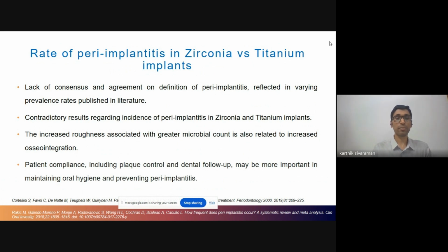The other aspect is for increasing the bone implant contact and increasing the osseointegration, we have increased the roughness of the implants. However, when there is gingival recession of the tissues around the implant and exposure of such threads, these threads tend to accumulate plaque, buildup of bacteria, and then they tend to encourage the formation of or lead to perimucositis and periimplantitis. Now, this roughness is generally seen to be more in titanium compared to zirconia.